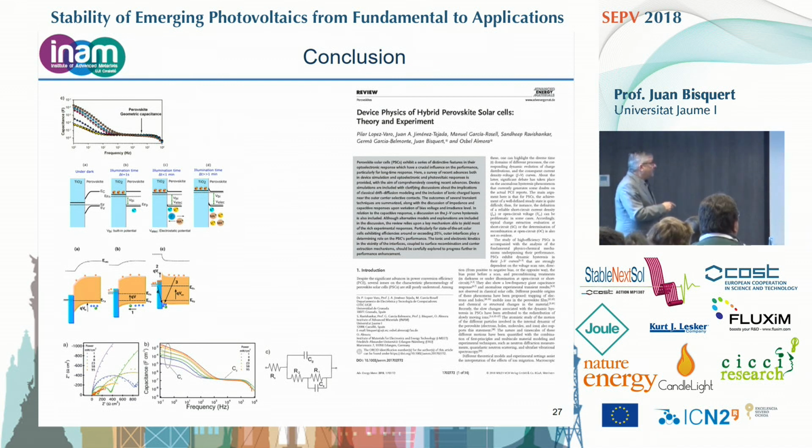In conclusion, we have a very good understanding of properties of the capacitance. This gives us a lot of information. This is the bulk sample, so we can correlate with bulk phenomena here. At lower frequency, we have polarization, but it's not only the ionic polarization. Under light, you start to flow, you bring positive, negative electronic, you induce more recombination, and in the end, the samples up to 18%, more or less, I think they are controlled by surface recombination.